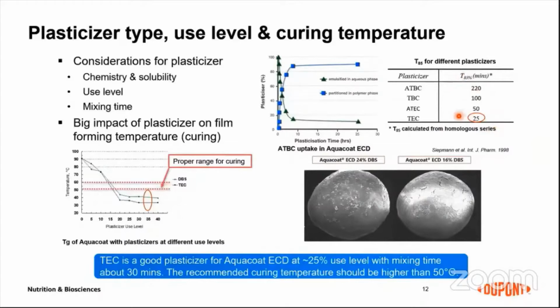And the different plasticizer may need different mixing time, like the hydrophobic one, ATBC, or the DBS. Usually you see here this data show the 85%, which means how many percent of plasticizer is present in the polymer phase. So the ATBC or DBS, those kind of hydrophobic plasticizers, we do need a much longer blending time to achieve the 85%. But TEC just less than 30 minutes, right?